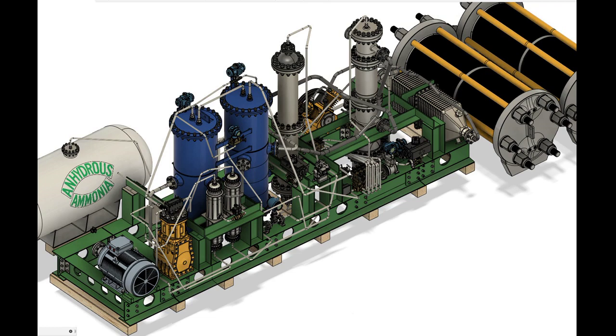Since the principal bulk of energy consumed in ammonia synthesis pertains to the production of the hydrogen feedstock, scale offers little to no opportunity to reduce energy demand other than easily avoided differences in heat transfer. Therefore, we can conclude that there is no intrinsic feature of mass-scale production that facilitates a marked improvement in process efficiency if heat transfer is held constant. This leaves only extraneous factors at play, largely isolated to the auxiliary systems, as opposed to the core reaction process.